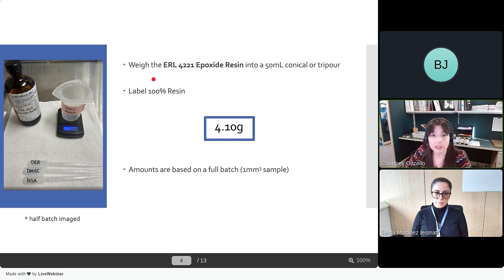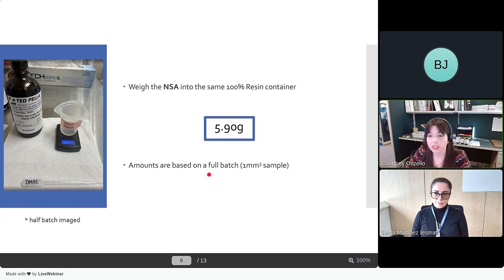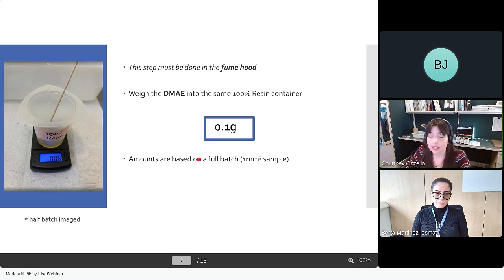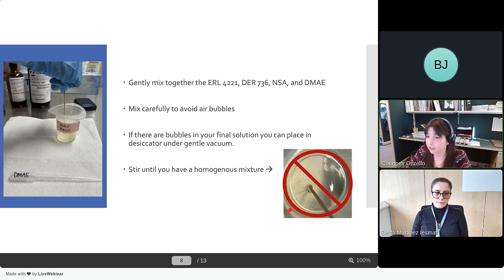So your first step is to tare your scale and weigh out 4.1 grams of your epoxide resin. And then to that, you'll add your DER 736, 1.43 grams, followed by your NSA, 5.9 grams. And then in the hood, you'll add your activator, and this must be added last, and you'll mix it into the 100% resin in the hood. And you want to continue to mix this until you get a homogeneous mixture.